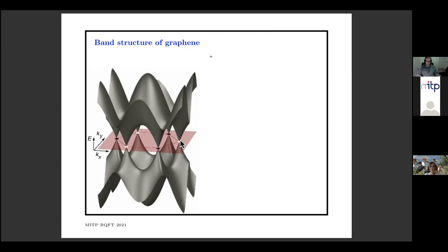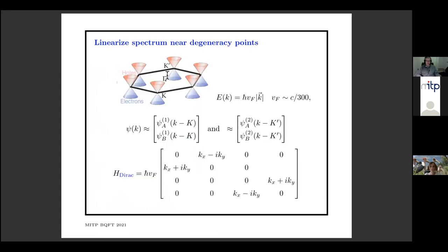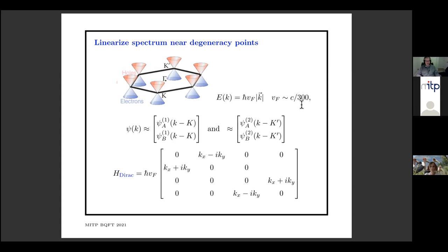The solution of the theory — the spectrum of the Hamiltonian — has two energy bands, depicted in this famous picture. These dark objects above and below are the energy bands. There's a particle-hole symmetry through reflection through the gray plane. These bands touch at discrete points, which is fairly generic in this dimension for a Hamiltonian with a complex off-diagonal hopping amplitude. In the Brillouin zone there are two inequivalent places where these bands touch. Moreover, charge-neutral graphene has the negative energy states — the lower band — completely filled, so it has a Fermi surface right at this degeneracy point.